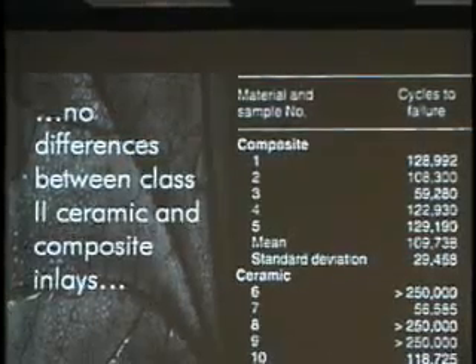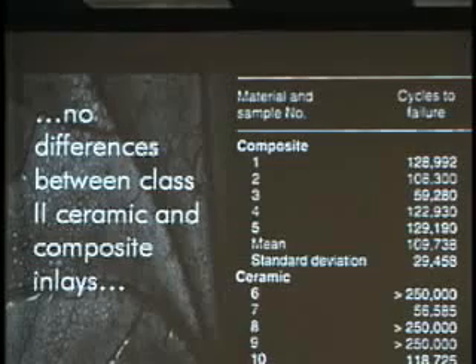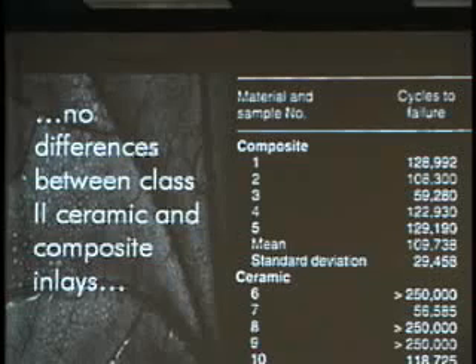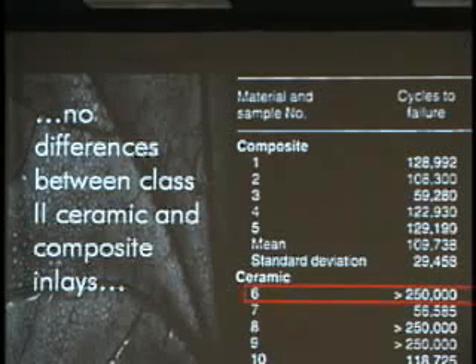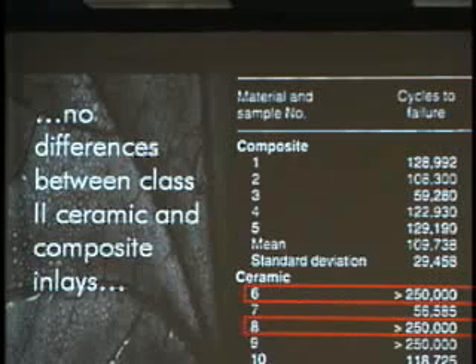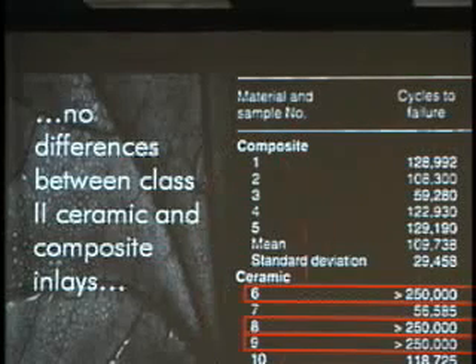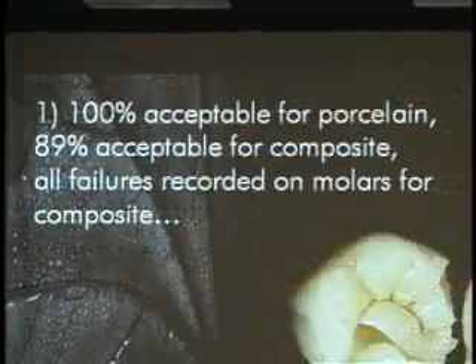Another study here in which they measured the number of chewing cycles to failure using 170 Newton of force, and again, it was very difficult to see a difference between ceramic and composite inlays. But very interesting in this study, they used a very small number of samples. I don't know how it could be published with only 10 teeth being tested in a load to failure test. It is really a small number.